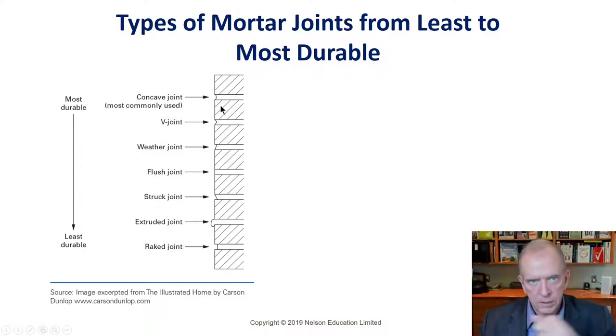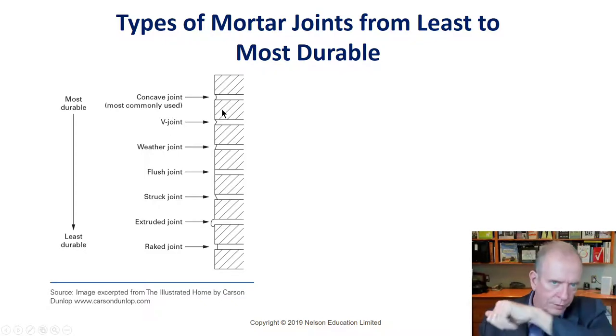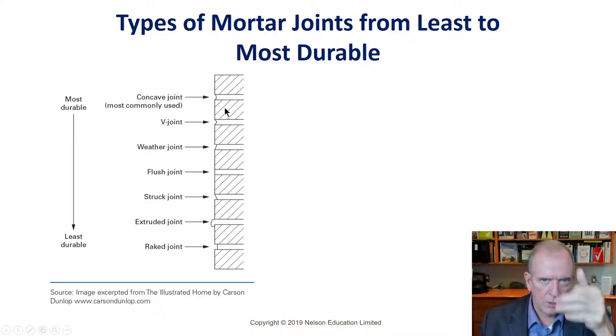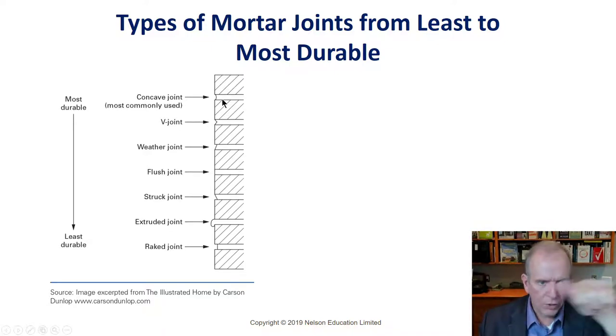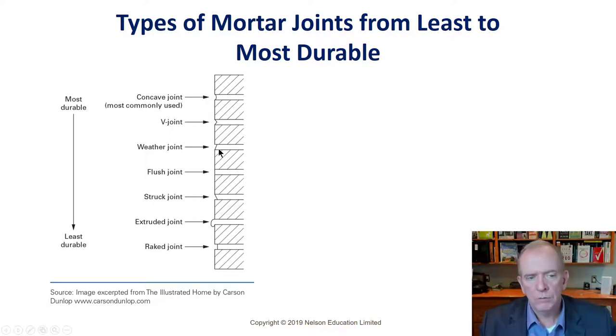The most popular mortar joint is the concave joint — very quick to do and very durable. After the mason clears off the excess mortar, they tool the joint with a concave jointer, doing all the vertical joints first and then the horizontal joints. The mortar should be about fingerprint hard when they do it so it will crumb and not smudge. The V joint is just as good but slightly harder to make look nice where the joints intersect. Both are compressing joints — when you compress the mortar on the surface, that helps seal the surface against moisture penetration.